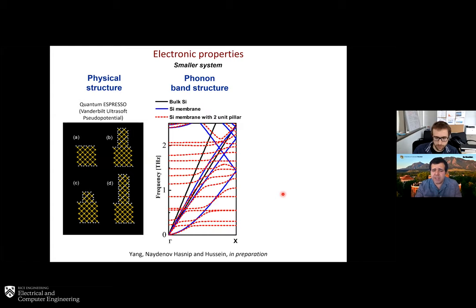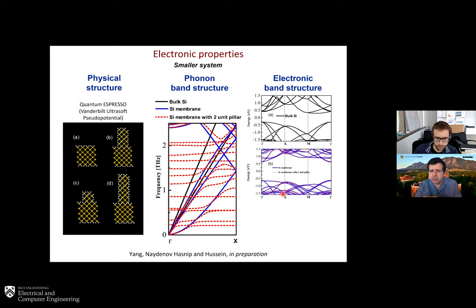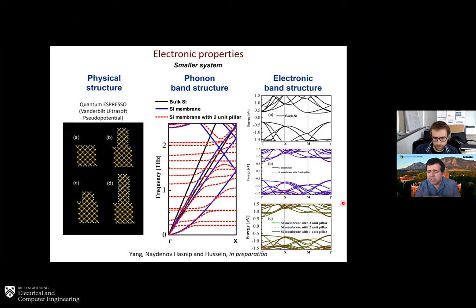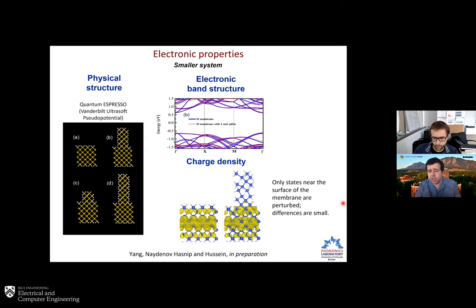We've looked at some NPMs and we've got the phonon band structure, but we also were able to obtain the electronic band structure. Shown there in black is bulk, then underneath it is membrane, and then a membrane with some pillar. You can see that the electronic structure hardly changes by adding the pillar, and even if we add larger height, it hardly changes. So this in itself is a positive indication. Furthermore, if we plot the charge density, we're already seeing that there is not much effect by adding the pillar. So this is ongoing work with Hasnip's group in York in England.